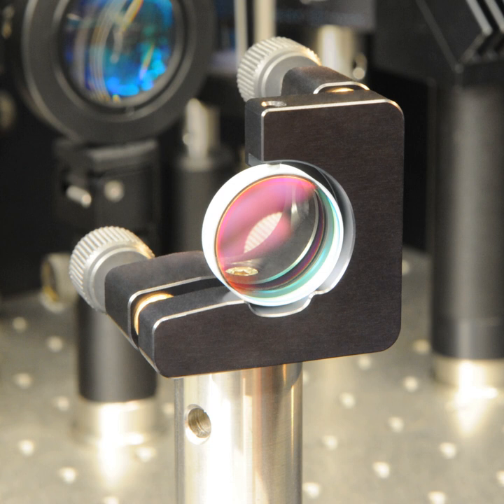The thicknesses of the layers are chosen such that the path length differences for reflections from different high-index layers are integer multiples of the wavelength for which the mirror is designed.